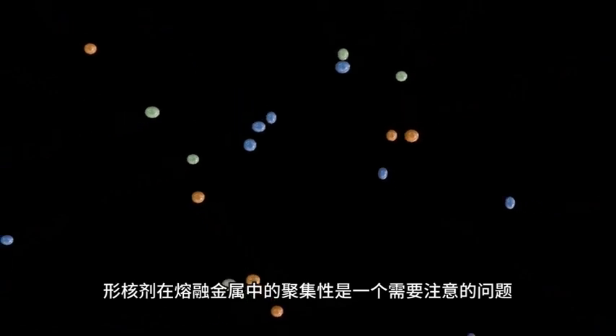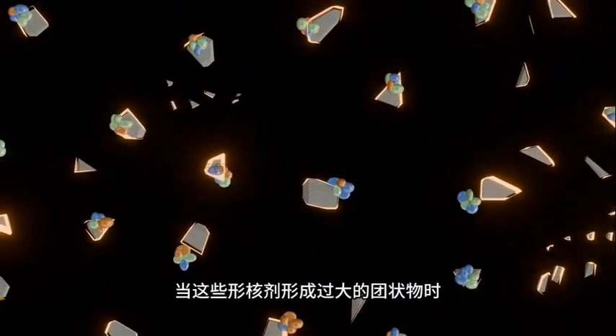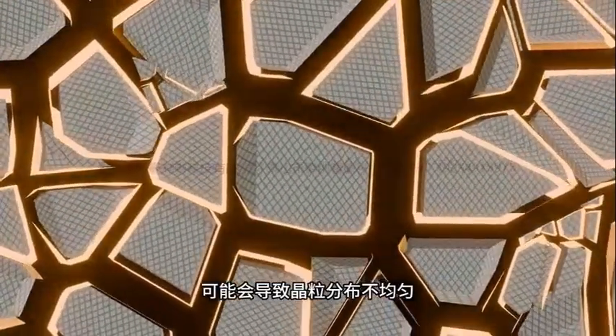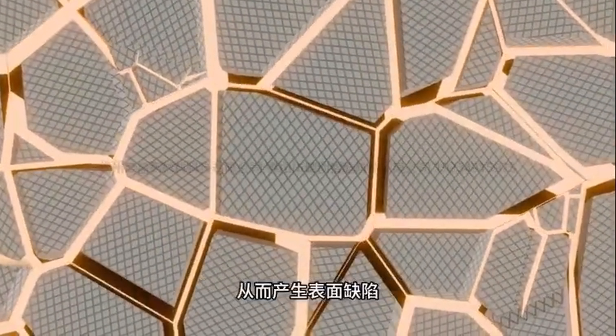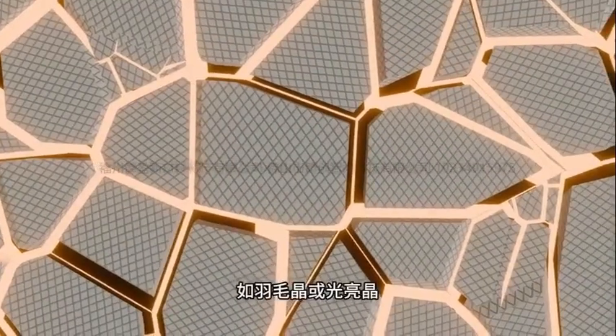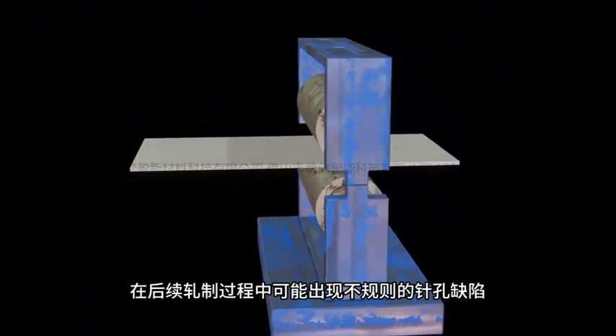However, the tendency of nucleating agents to agglomerate in molten metal is an issue that needs attention. When these nucleating agents form excessively large clusters, they may cause uneven grain distribution, leading to surface defects such as feather grains or bright grains. In particular, if the size of these clusters exceeds the final thickness of the metal, irregular pinhole defects may appear during subsequent rolling processes, affecting the final quality of the material.